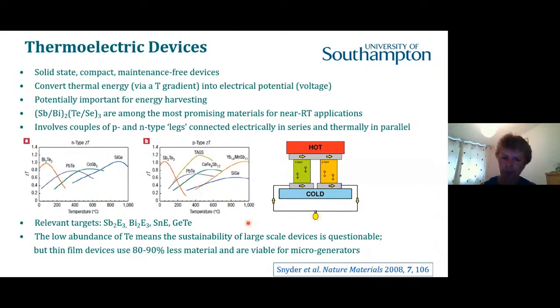Another comment about thin film materials is that if we're thinking about thermoelectric energy harvesting, if we want to use large-scale thermoelectric devices based on something like bismuth telluride or antimony telluride, we have a problem because tellurium is one of nature's lower abundant elements. There aren't large supplies of tellurium. So in terms of having a sustainable energy solution, bulk thermoelectric generators based on the tellurides is unlikely to be a sustainable solution.